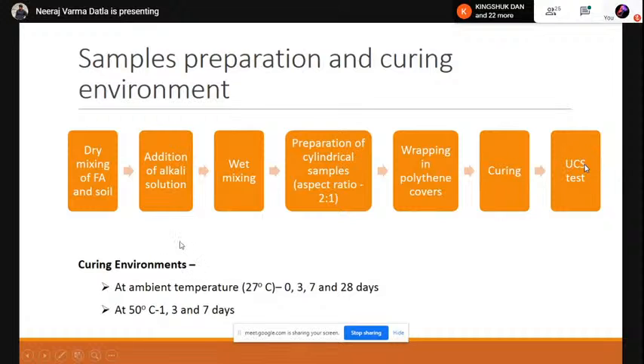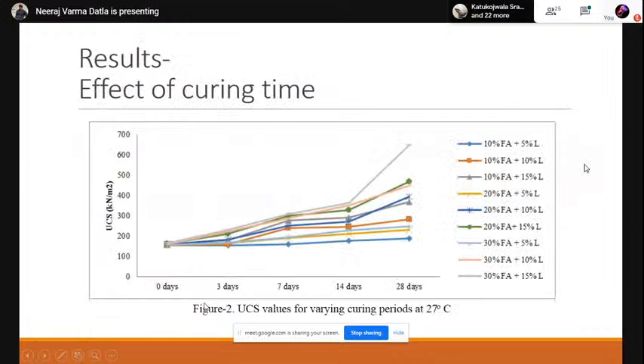Two curing environments are taken. One is ambient temperature for 3, 7, and 28 days, and the other is at 50 degrees centigrade for 1, 3, and 7 days. And these are the results of curing time. With increase in curing days, the strength of the soil increases.